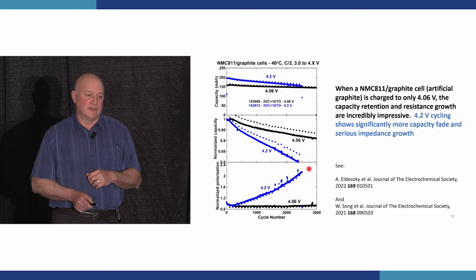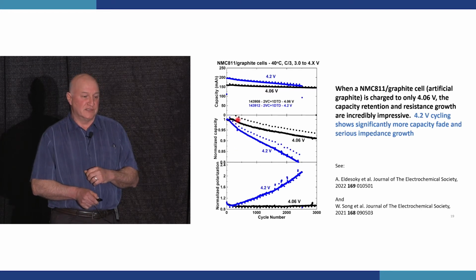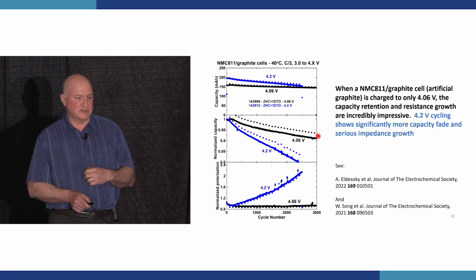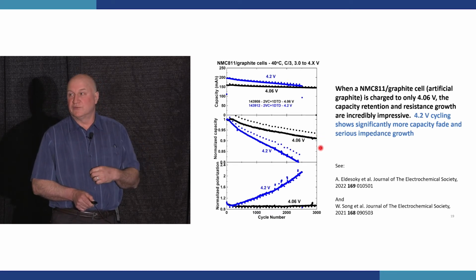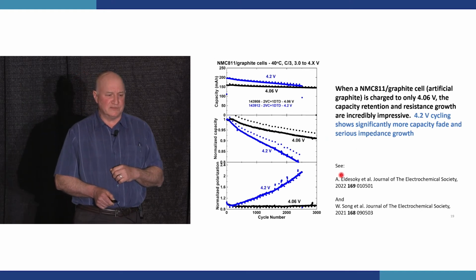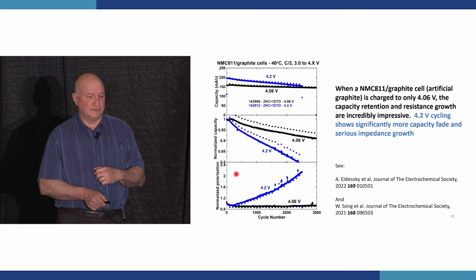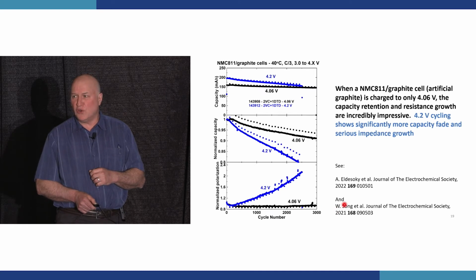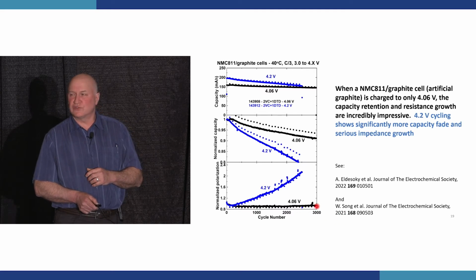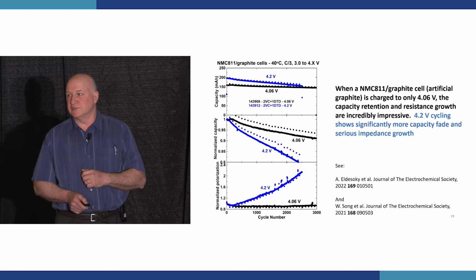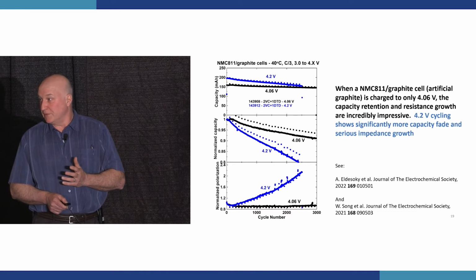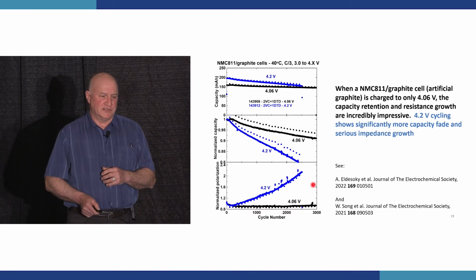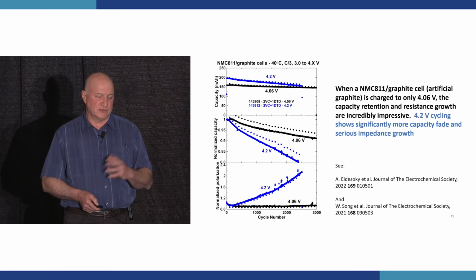2 years. And if you look at the normalized fractional capacity, after these 2 years of running at 3,000 cycles, you still have 90% capacity left in the 4.06 volt cell. But most impressive is if you look at the lower panel and you look at the voltage polarization normalized to cycle 1, the cell tested at 4.06 volts has had no increase in internal impedance at all in these 3,000 cycles. It's incredible. And the cell that's going to 4.2 volts has had a doubling of its internal impedance. Well, that's bad, right? So if you want to see the data, you can look in these particular papers, more explanation.